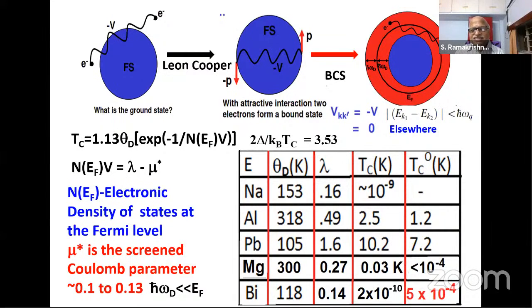Aluminium, the TC given by BCS is 2.5. The TC observed is 1.2K. So it is not very surprising. The important thing many people miss out is that BCS theory never predicts the correct temperature. BCS theory tells you what is the mechanism which leads to superconductivity. So people blame the BCS theory because they thought that it should accurately predict the TC. No, because each material has its own Fermi surface, all other complications coming in, which is not being considered by BCS. They just put the interaction as minus V, that's all, and it is zero elsewhere.